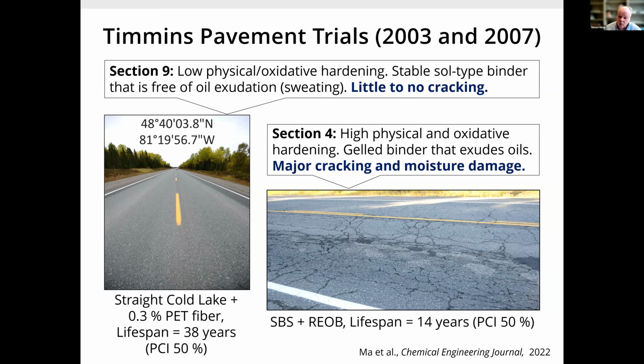On the right, quite contrasting, a Superpave mix with highly modified SBS and some motor oil. You don't mix motor oil, a lubricant, with a highly modified binder because you get a gel, and a gel every day and night, it shrinks and expands and it squeezes out a tiny amount of that lube oil, which gets to the aggregate, and you get this kind of a performance. 14 years, about a third of the regular asphalt without any additives from Alberta.